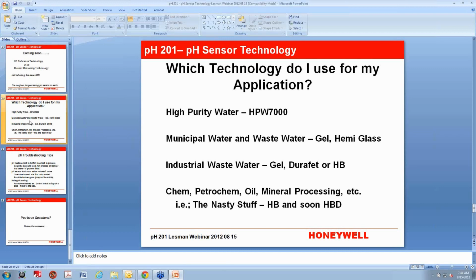In general, if you have high purity water, you need something like an HPW 7000, which is our high purity water device that has a flowing reference. It's made of stainless steel. It has a good mixing chamber. It has a solution ground to give you a very stable measurement. And that's really the only thing that will work in high purity water. High purity water is any water that is less than 20 microsiemens conductivity.